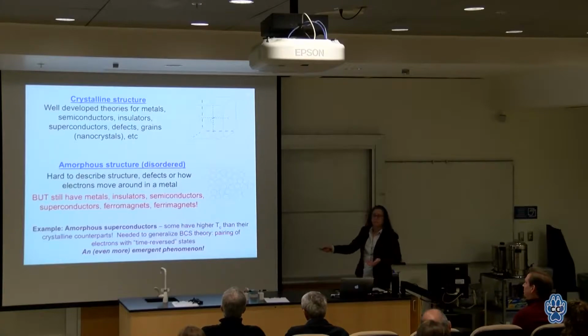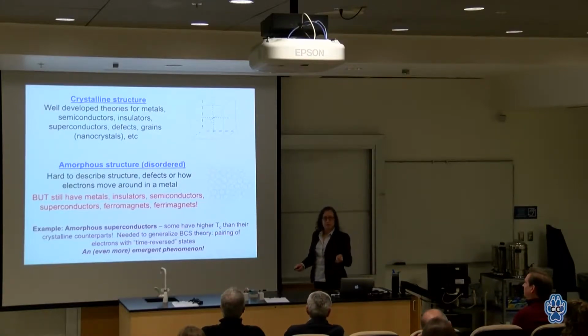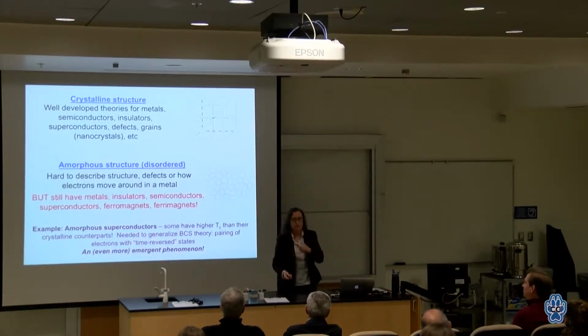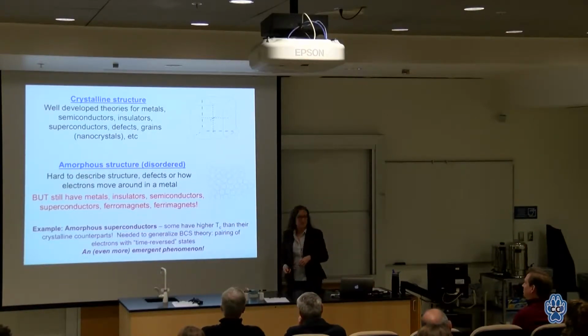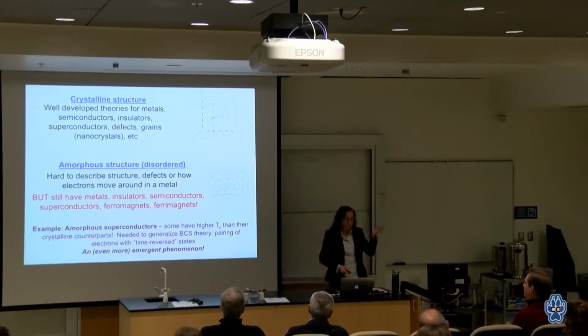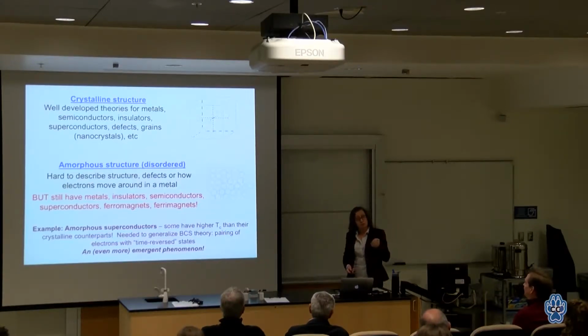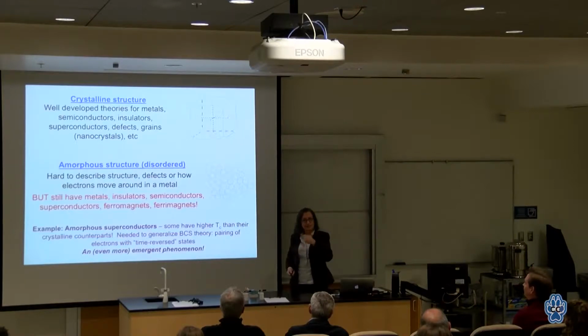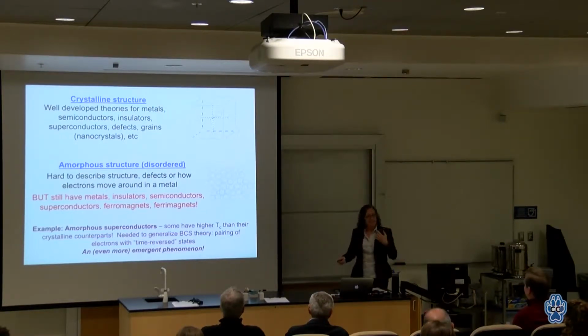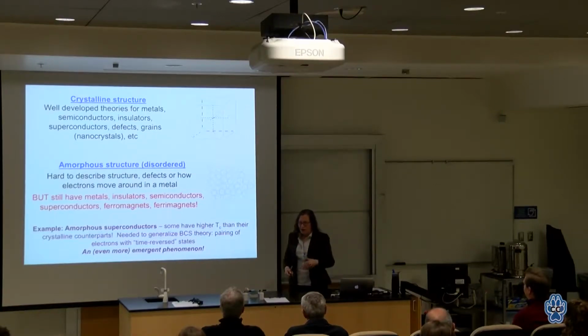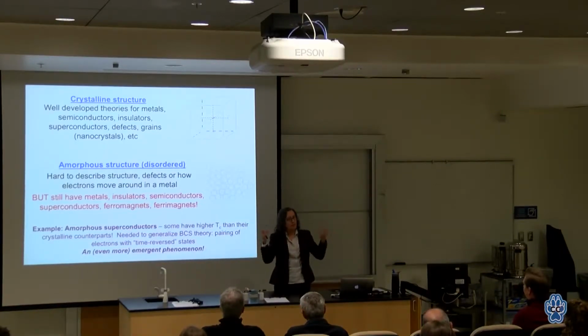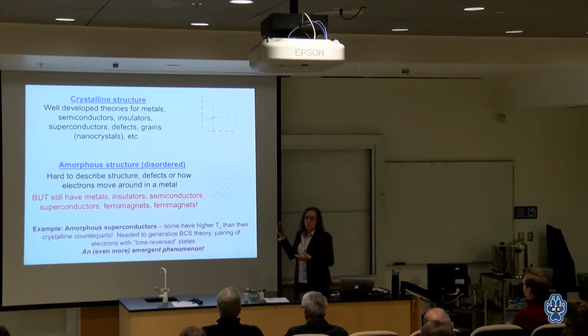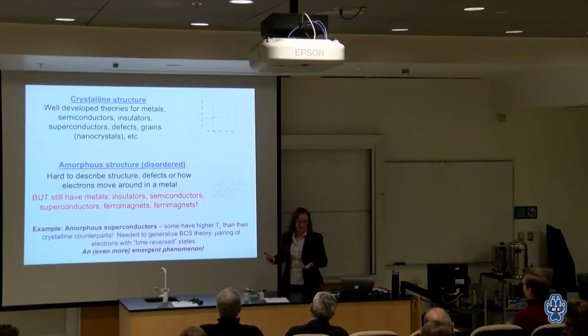One of the interesting things that many people don't realize is there are superconductors that have higher superconducting transition temperatures than their crystalline counterpart, molybdenum. Crystalline molybdenum is about a 1 degree superconductor. Amorphous molybdenum is about 7 degrees. So I love that generalization. And as an experimentalist, which I am, I love the playground of the periodic table, but even more than that, I love the idea that I can force the theorists to generalize their theories.